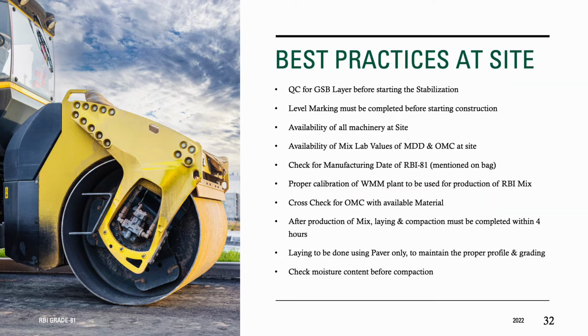Besides having a proper design and a well-defined methodology, quality control at site is of utmost importance in order to achieve the desired results. The following checks should be kept in mind while working with the stabilized pavements. Once the mix has been paved, moisture content of the layer should be checked and corrected if needed before compaction. Laying and compaction must then be completed within 4 hours of mixing, otherwise proper compaction and related density may not be achieved.